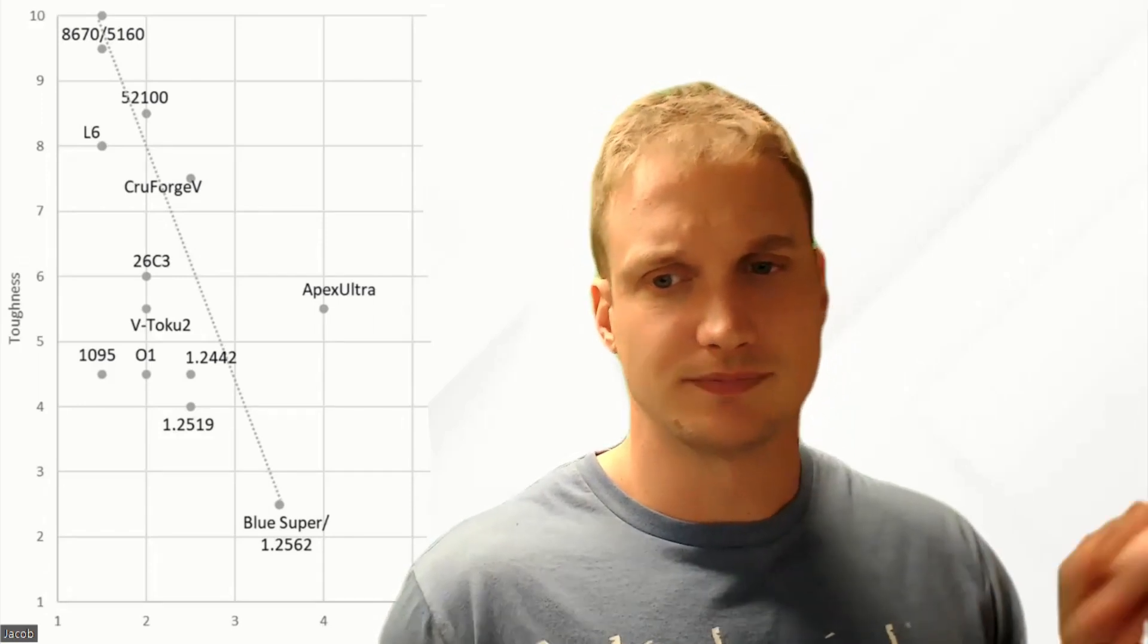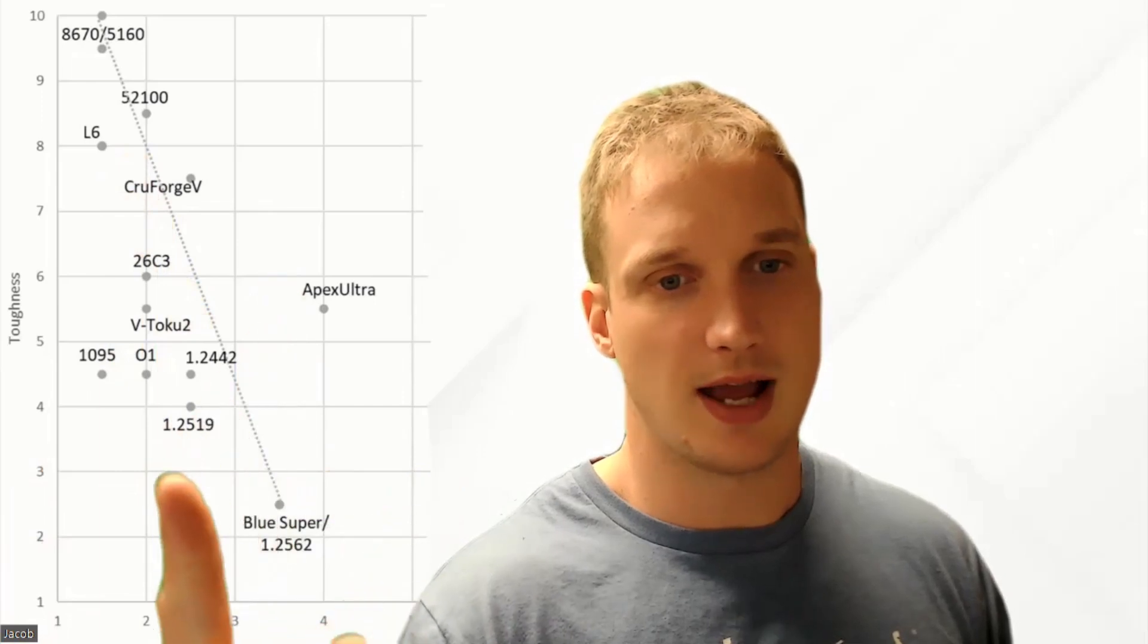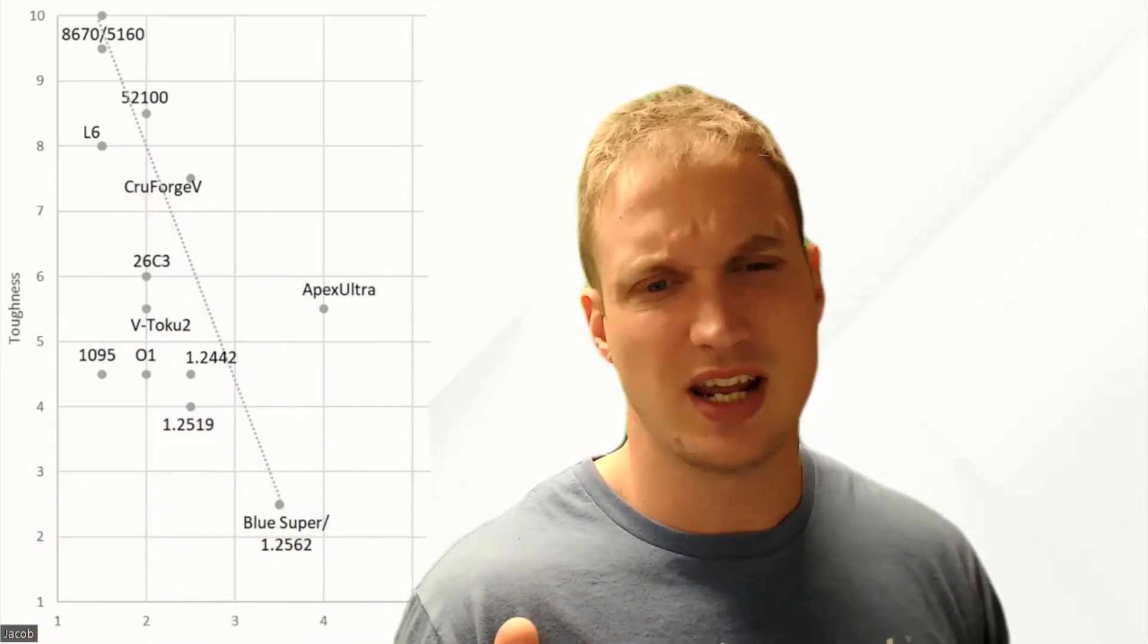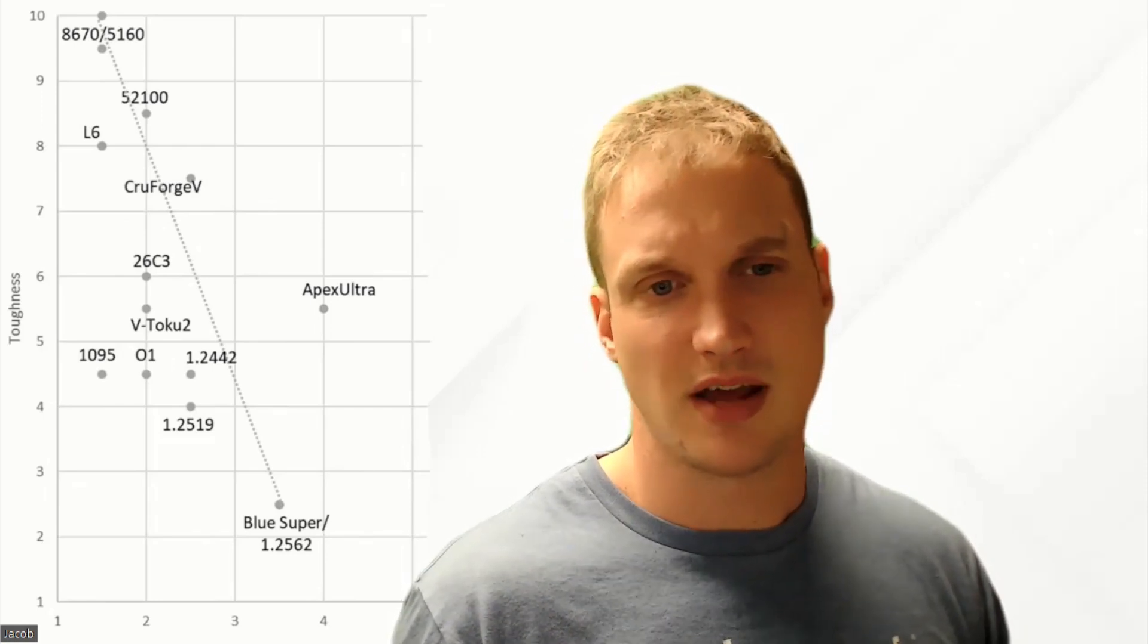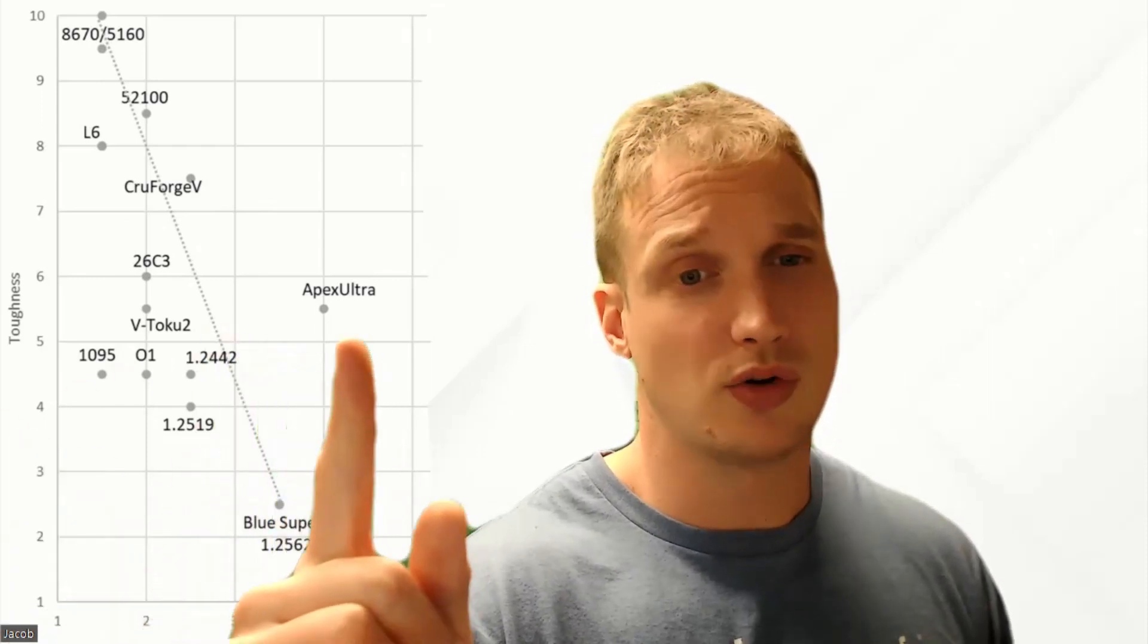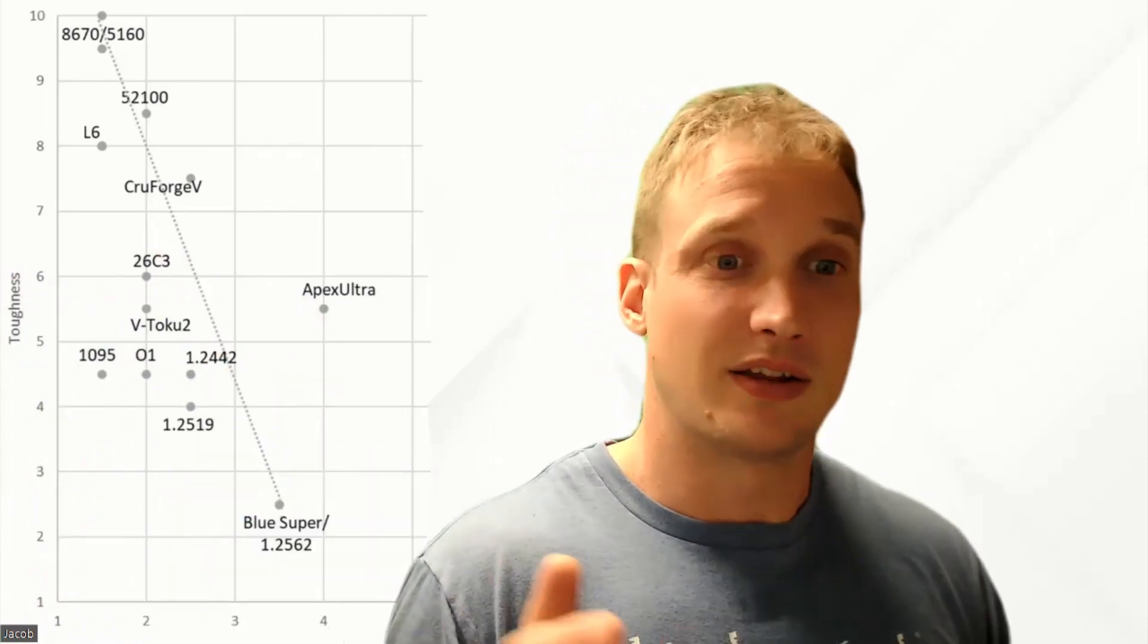Whereas if you're using a folder in an urban work environment, your cardboards, your papers, your straps, all of that stuff's incredibly high abrasive. But again, we're talking about bushcraft type stuff here. You're not going to notice an edge holding difference between 8670, 5160, and 1095 if they are ideally heat treated. So you are getting essentially better than double the toughness of 1095 with 8670 and with 5160 as well. Now, this line that you see here, this is kind of our ideal performance line here and kind of our standard line. So our standard line goes from super blue to 8670.